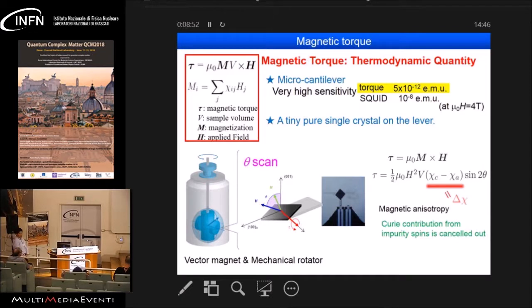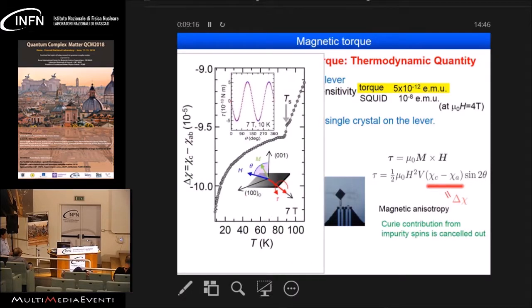So to do this, we want to quantify the magnetic signal, and we measure the magnetic torque, which has very high sensitivity by using this kind of micro-cantilever technique. And the sensitivity is much higher than commercial SQUID magnetometry. So what we can do here is rotate the magnetic field like this and measure the torque as a function of angle theta, which is from the c-axis. And you can see this kind of sine 2 theta curve, and the amplitude of this oscillation is proportional to the difference between the c-axis and a-axis susceptibilities. So we call this difference delta chi.